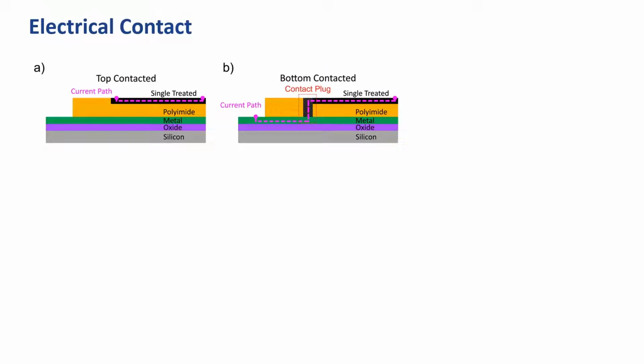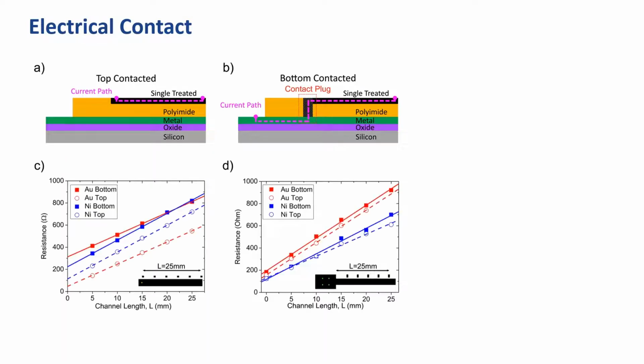Electrical characterization of this contacting stack was carried out through a modified transfer line measurement, whereby resistance measurements are taken at each of several points at known separations along a well-defined channel width. In structures without a contacting plug, the top surface is electrically isolated from the base by the insulating residual polyimide. Therefore, we can measure the resistance through a given length of laser-induced graphene when both the probe needles are on the top surface, which we denote as top contacted. And when one is placed on the base metal and one on the top surface, we call this bottom contacted.